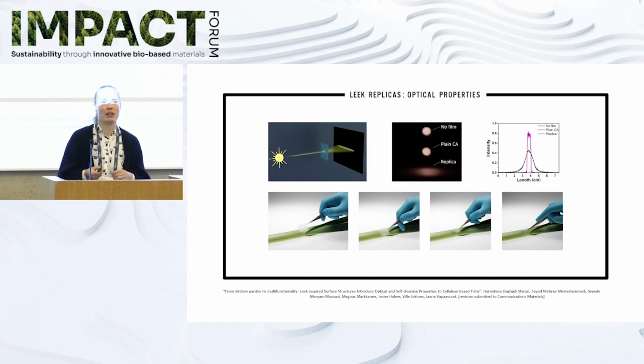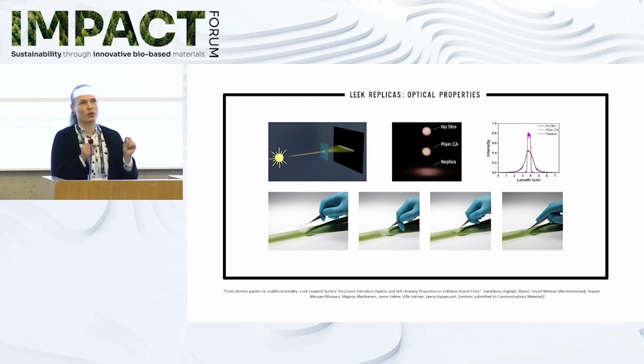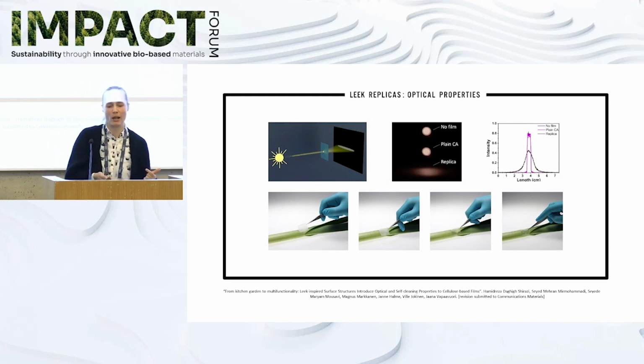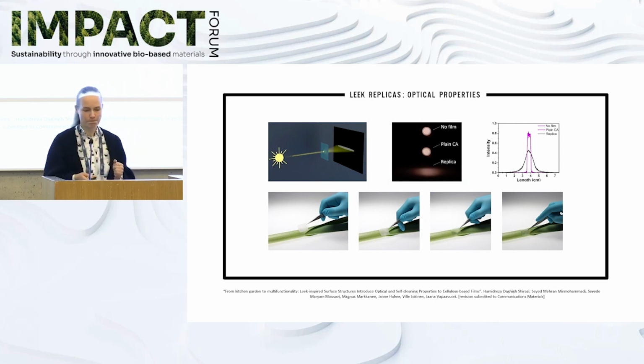This was also something that we then noticed when we put these films on top of a perovskite solar cell. So thanks to both this diffusive transmittance and that they also exhibited anti-reflection properties, we could increase the power conversion efficiency of the solar cell below these substrates.